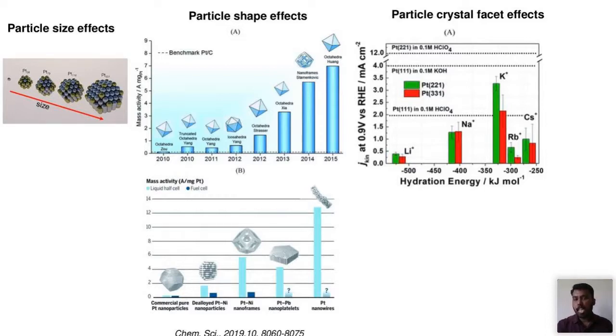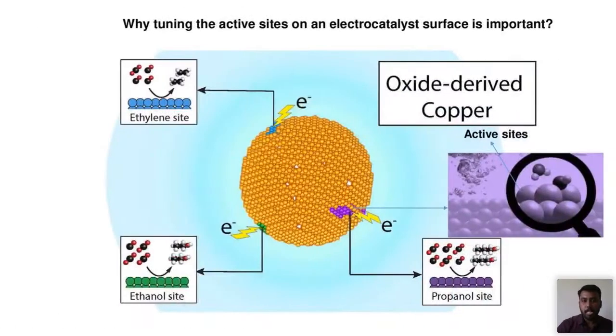So creating the pores is very important in electrocatalysis. Based on the crystal planes also, the electrocatalytic activity can be influenced. And also based on the transition or alkali metal ions present in the electrolyte, you can tune the electrocatalytic activity. Like the material selection, electrolyte selection, potential window selection, all matters. And also the structure. For example, if you have a commercial pure platinum particle compared to the solid particle, platinum nanowires perform better. And also Pt-Pb nanoplatelets, like lead and platinum alloys, perform better.